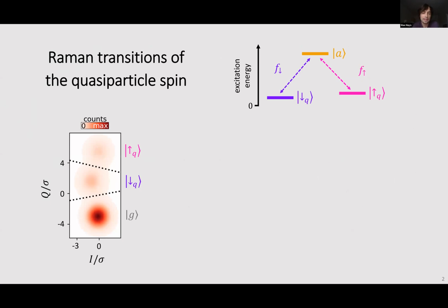So second part. I talked about how we can detect the spin in the last talk. This is showing the full IQ histogram for the resonator reflection coefficient again, and we can detect these 2 spin states in the ground state. Throughout this portion, I'm going to be presenting data in terms of the probability of finding the quasi-particle in a particular spin state, and we determine these just by these thresholds shown in this plot, these dashed black lines. Our goal is to achieve spin manipulation by using the Andreev levels as a lambda system. We're going to use the 2 spin states of the lower doublet, and I'm going to label one of the states in the upper doublet A, for ancillary.